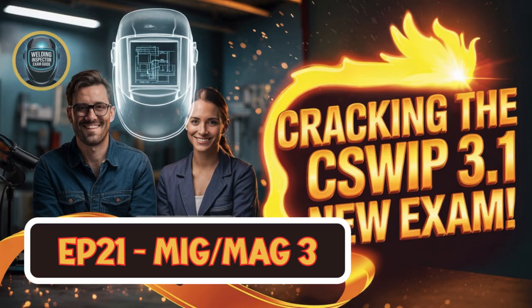It might seem simple, but here's the key insight, right? WFS directly dictates your welding current. That's the core relationship. Increase the wire feed, and the current automatically goes up. Precisely. This direct link means controlling one effectively controls the other. It's the main way you determine how much metal you're actually putting into the weld. Which affects everything else. Penetration, bead shape, everything. And you'll typically see standard wire diameters like 0.6, 0.8, 1 millimeter, up to 1.6 millimeter.